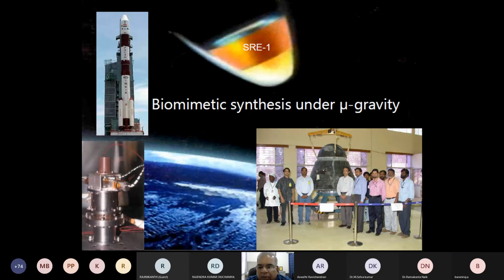Whereas if you see human bone, it's around 3 to 5 nanometers, right? That means that in human bone, in biology, the supramolecular matrix has much better control. So the concept came to us: if we can carry out an experiment where gravitational force is not there, then the supramolecular matrix will have a better scope to exert its control. With that philosophy, we did it.